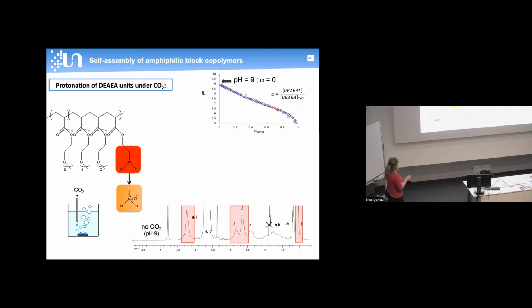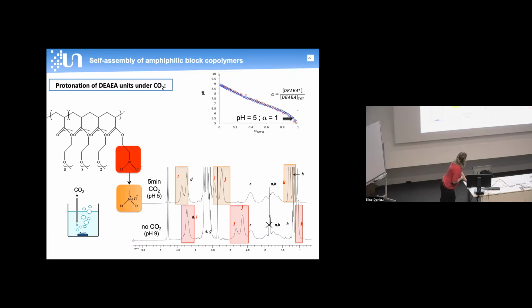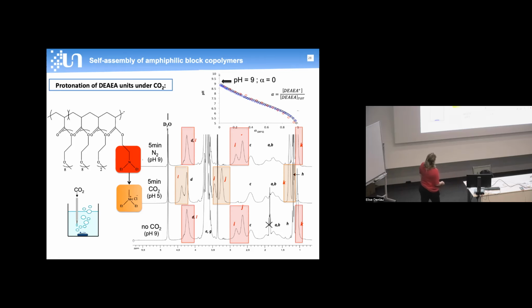So then the protonation of the amine with the carbon dioxide bubbling in water was followed by NMR. And here you can see that the resonance peaks, which are characteristic of the amine function, highlighted in red, exhibit a downfield shift, which indicates the protonation of the amine after 5 minutes of carbon dioxide bubbling. And after 5 minutes of nitrogen bubbling, the initial spectrum was completely recovered, showing the reversibility of the process.